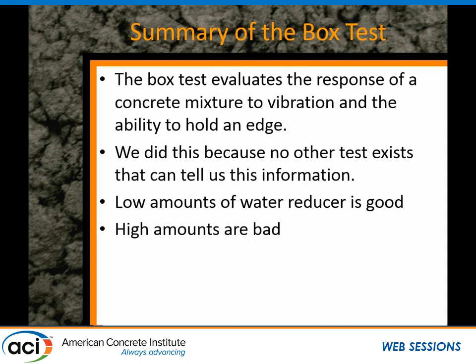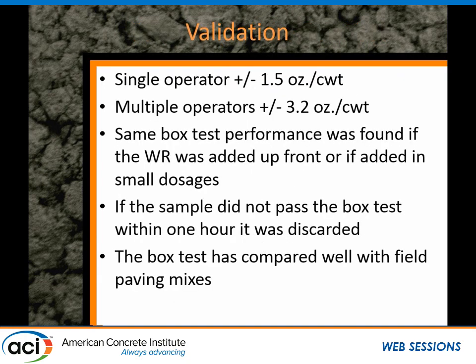The box test evaluates the response of a concrete mixture to vibration and the ability to hold an edge. We did this because no other test exists. The slump test tells you nothing about how a concrete will pave — it's a great consistency test, but it doesn't tell you how it's going to pave. Low amounts of water reducer is good; high amounts are bad. Single operator variation in this test is published: plus or minus one and a half ounces per hundred weight; multiple operators, about 3.2. If the sample doesn't pass the box test within an hour, we throw it away.